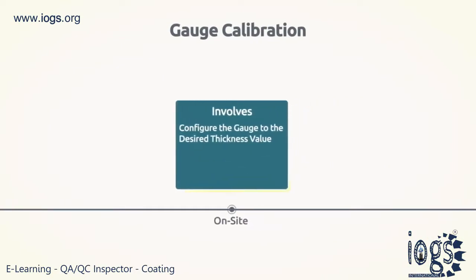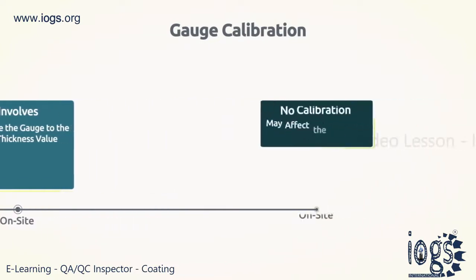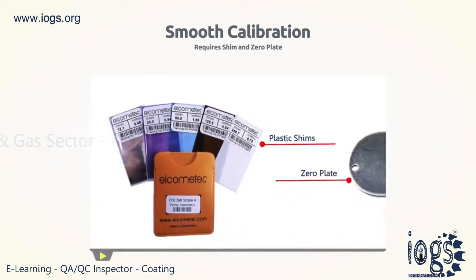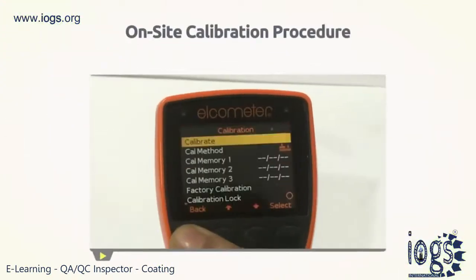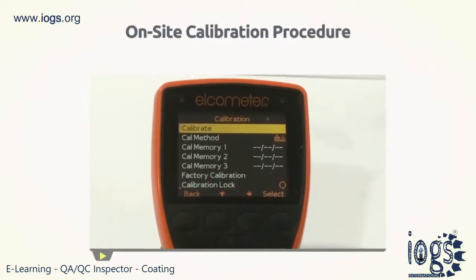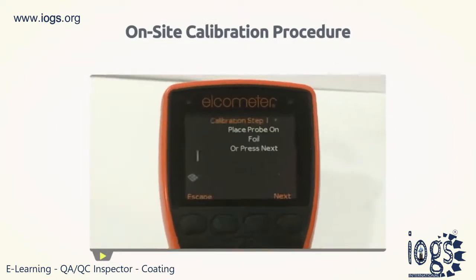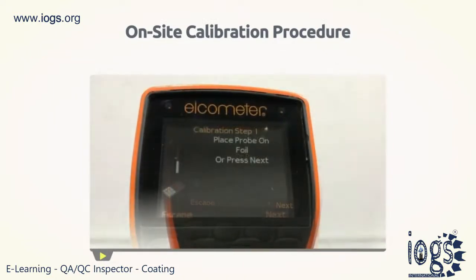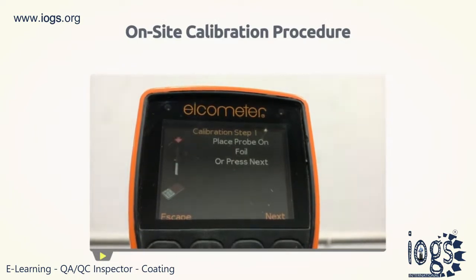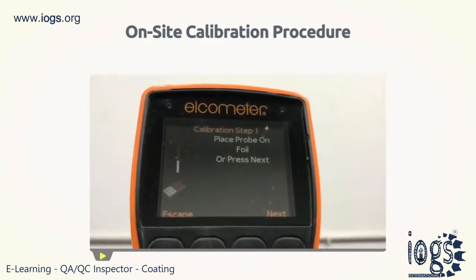Calibration adjustment involves configuring the gauge to your desired thickness values. It is best to calibrate the gauge on site before taking the gauge reading of the coated surface. Anything contrary to this may affect the accuracy of the results. Calibration is done by choosing the proper plastic shim with the above target DFT value, alongside an uncoated base or zero plate. To calibrate the gauge, press the Cal Soft key present on the gauge, locate the Calibrate option on the screen, and choose the same. You will now be presented with simple on-screen instructions that you can follow to calibrate the gauge successfully.